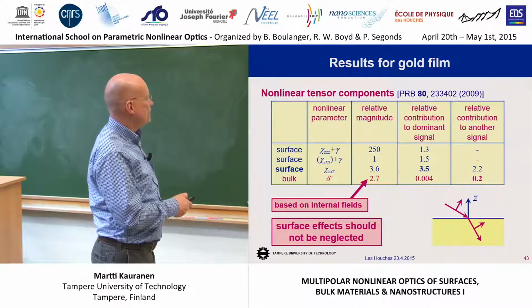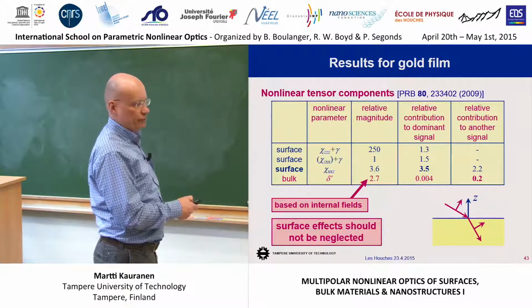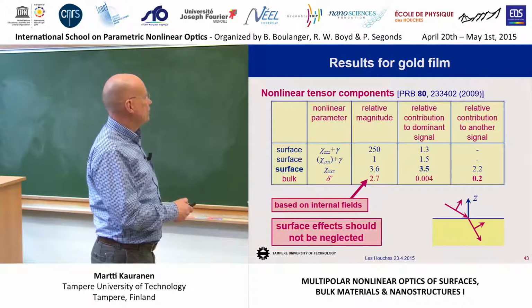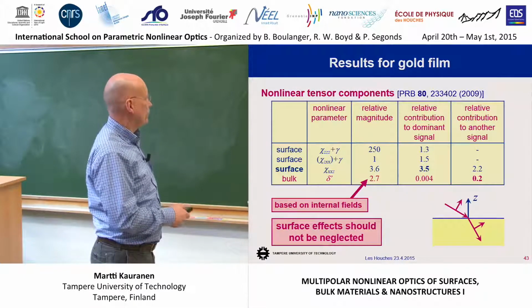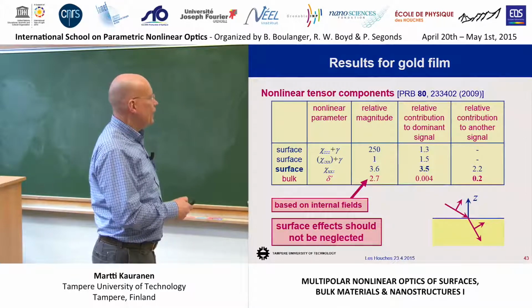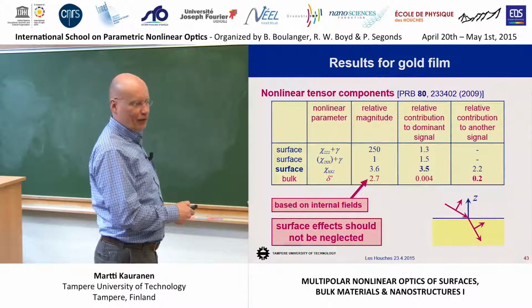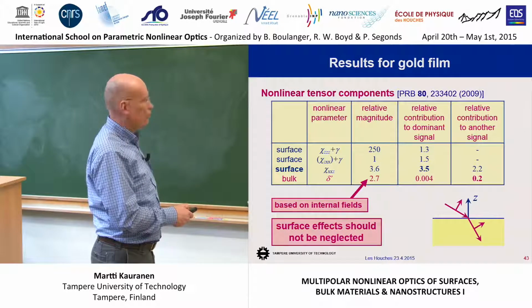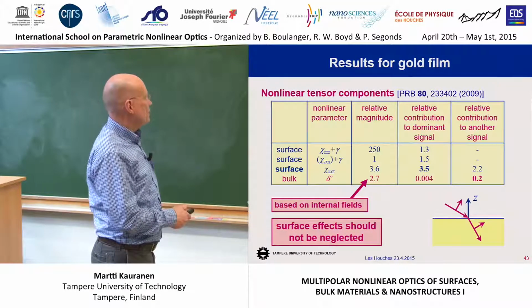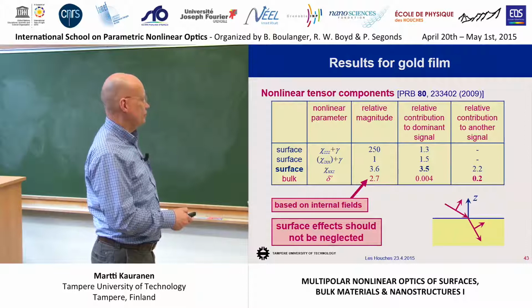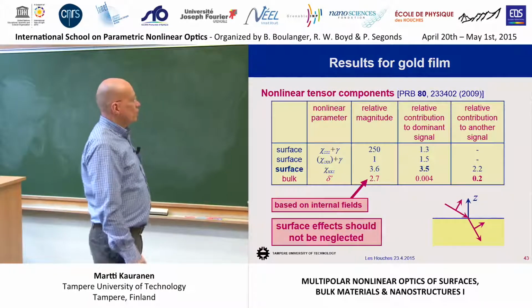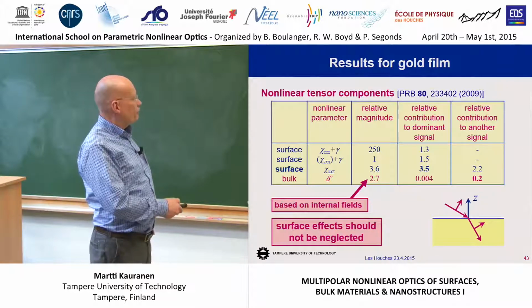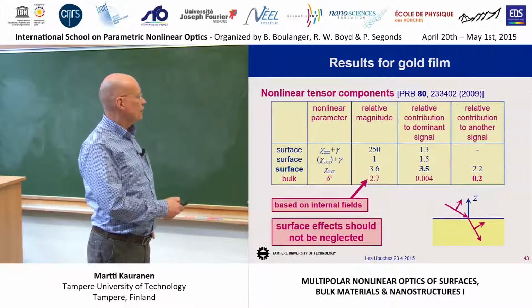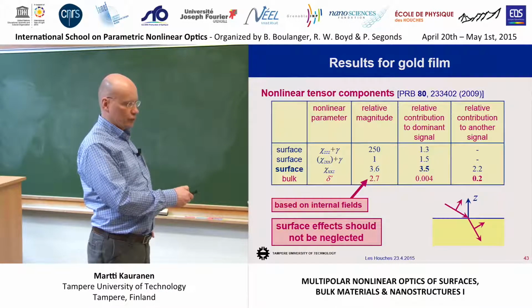Here's a surface parameter ZZZ, huge, 250. ZXX, which is actually within the free electron theories, there's, for metals, this ZXX surface component is actually only due to this gamma bulk parameter. Very interesting. That would be 1 in our case. We normalize here. XXZ surface contribution 3.6. Bulk parameter delta prime 2.7. Okay. So we measured the bulk parameter, no question about that, but clearly the surface effects are important also.